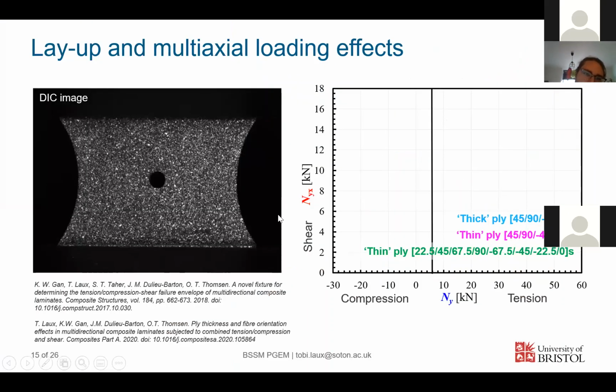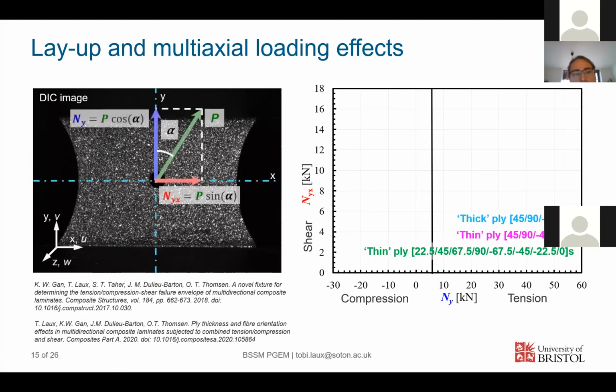Now the specimen we came up with to test this, and you can see here the specimen with the speckle pattern for DIC, is this. It's an open hole specimen. And what we can do is, if we know the loading angle and we know our load, we can back out the normal component of this load on the gauge section and the shear component, and we can draw a failure envelope.